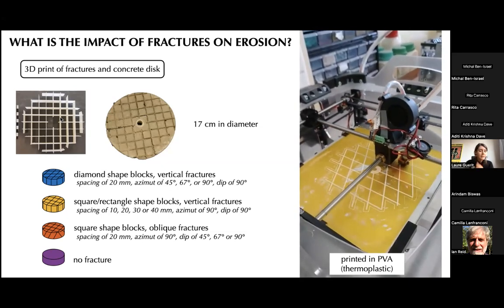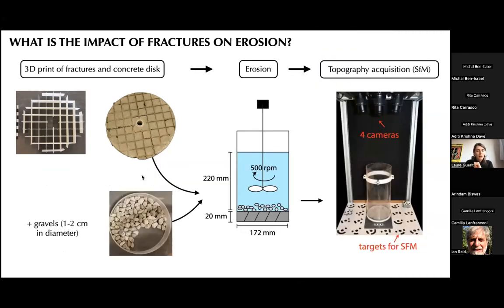When the discs are dry, we add some gravel on it. So we use gravels that are 1 to 2 centimeters in diameter, and then we use a setup similar to Sklar and Dietrich to induce erosion. To record the topographic evolution of the experiment, we use a system of 4 cameras to acquire pictures with different angles so that we can reconstruct the topography by structure from motion.